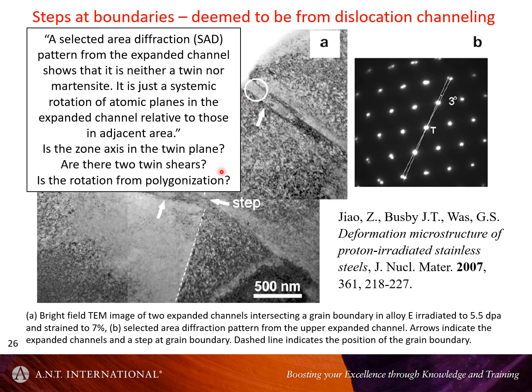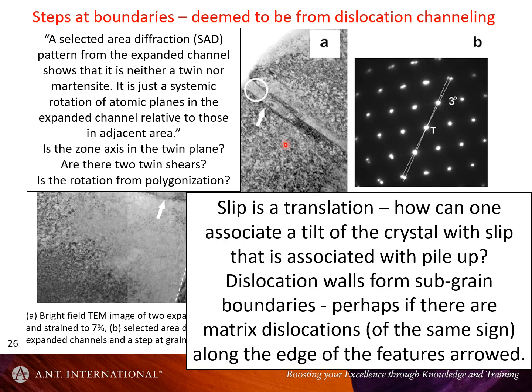It could be a twin, and we're just looking at it at a particular 1-1-0 direction, which doesn't show up the mirror symmetry. Could also be a crystal where you've had two twins, in which case you go from a tilted sample back to being in register again. So if there were two twin shears, you wouldn't see them. And whatever that feature is, which looks odd, and I hate to say what it is, the rotation could also be from polygonization. If you had a string of dislocations which had all butted up against this barrier, if you call it a barrier for some reason, then you would create something that would be like a polygonized wall, and that would give you a small tilt.